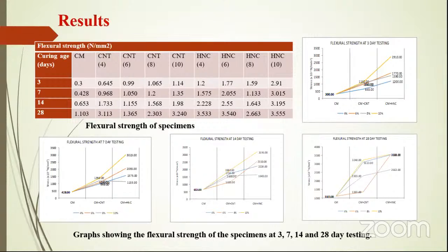As you can see, the flexural strength at 3, 7, 14 and 28-day testings. In all the graphs, even though there is a constant increase of cement strength from 3 to 28 days, it is still less than the cement nanomaterial composite. And what we observe here is that the strength gain of HNC at 3-day to 7-day to 14-day to 28-day is quite rapid. Even at 3-day, there is considerable strength.